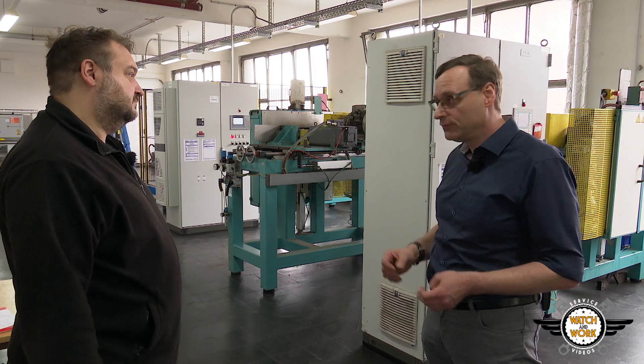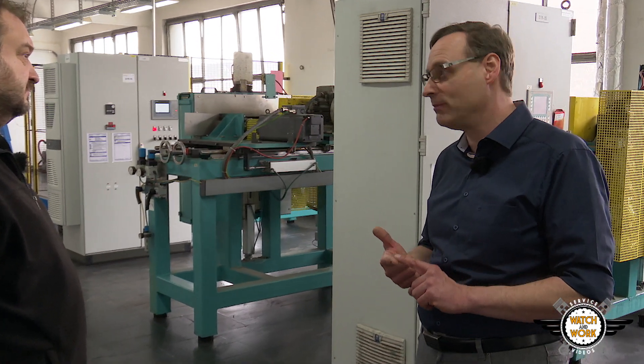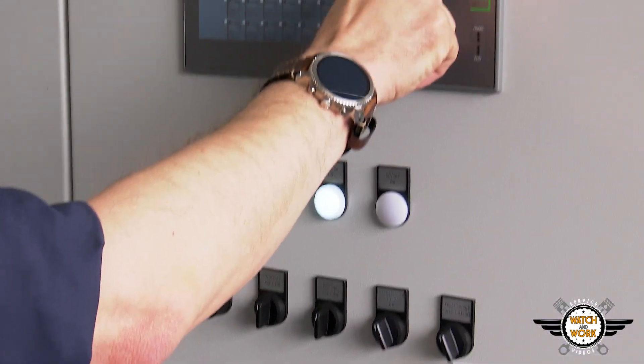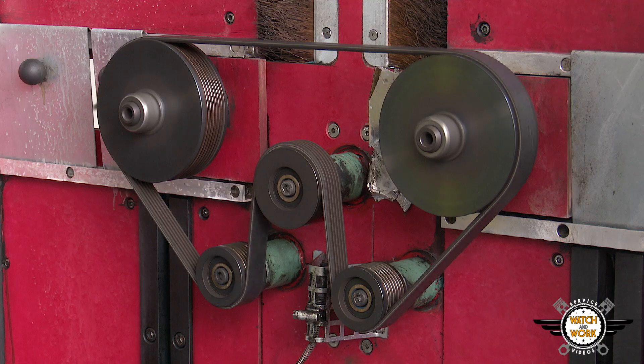It's about to get much warmer as the test rigs in our endurance testing section run around the clock, so they give off quite a bit of heat. We conduct tests on over 150 test rigs under all sorts of different conditions — cold, heat, mud, water. However, our work mainly focuses on continuous operation at high temperatures to check the belt's service life. We aim to replicate a service life of 150,000 km in 150 hours. What's important is that the belt emerges at the end with the same pattern of defects as after 150,000 km of operation. So the belts are tested under overload conditions, as we would otherwise have to test them for years before getting any results.